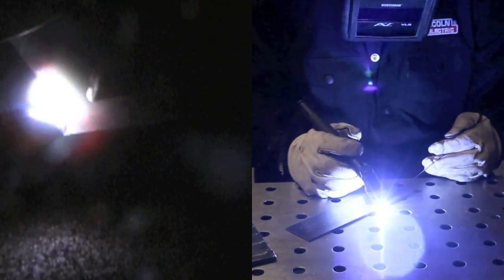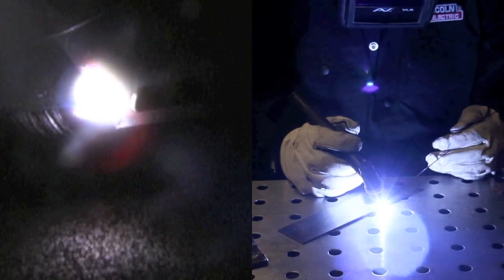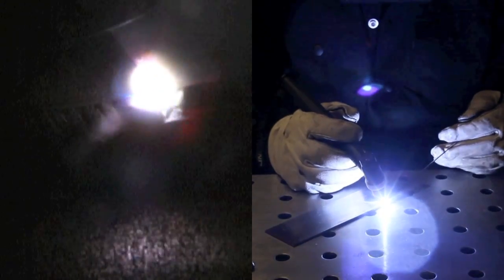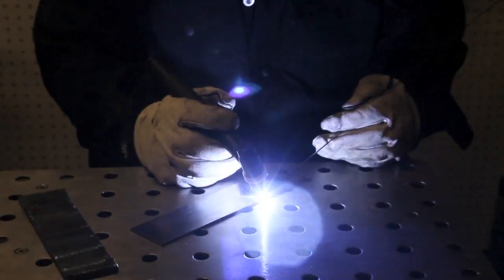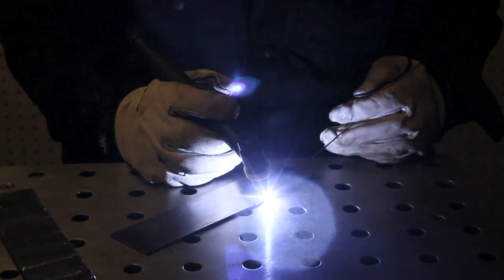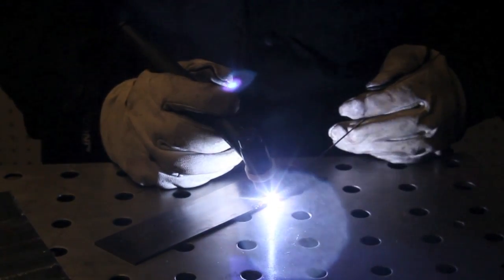Now you hear the 33 pulses a second, but the actual puddle and arc looks like a lot lower pulse rate, and that's just a phenomenon of the camera shutter speed and whatnot. What I hope you can see here, though, is I'm able to place that bead very precisely, and the edge of the bead kind of stays right on the edge of the metal. It doesn't want to roll over and melt it off too much. It allows me to stack a nice high profile bead up there right on the edge without it melting that edge over. It stays where I put it. It allows for a little bit more control than you would have without pulse, and that's important.